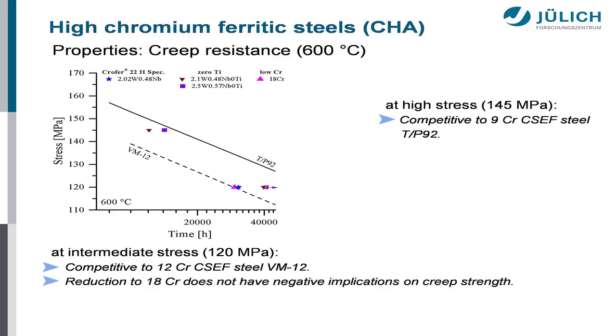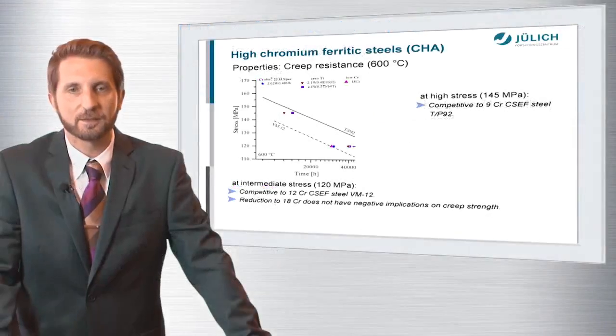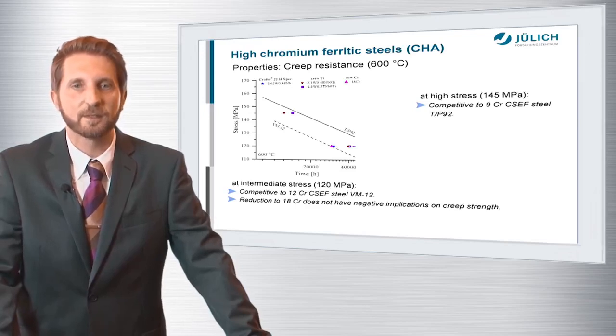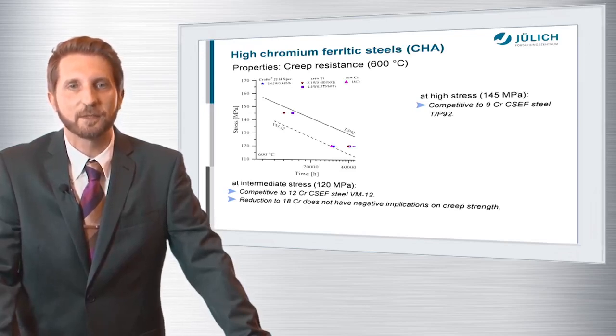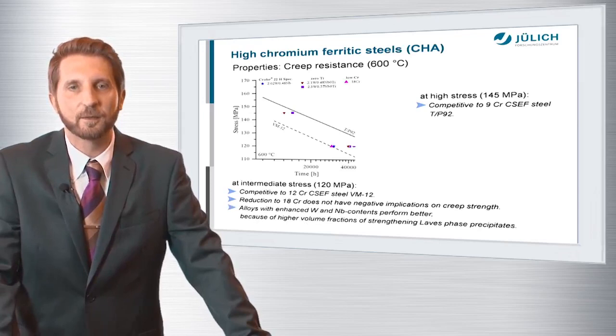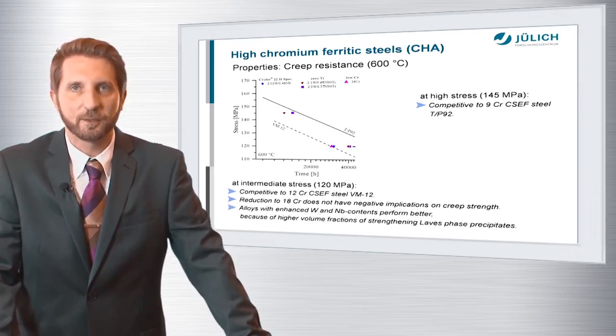What is a very interesting and important finding in this circumstance is that the reduction to 18% in chromium does not have negative implications on creep strength. So just compare the creep performance of the original Crofer 22H specification and the low chromium, the 18 chromium version. You see that there's not a big difference, and this is really an interesting finding which was documented in the award-winning paper.